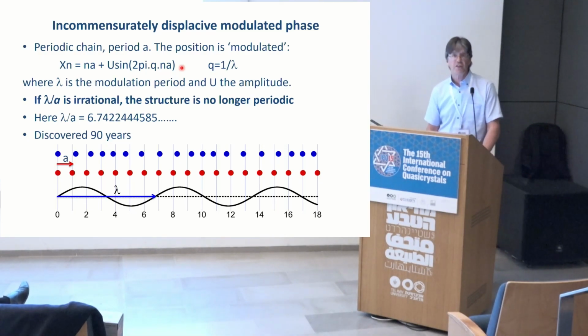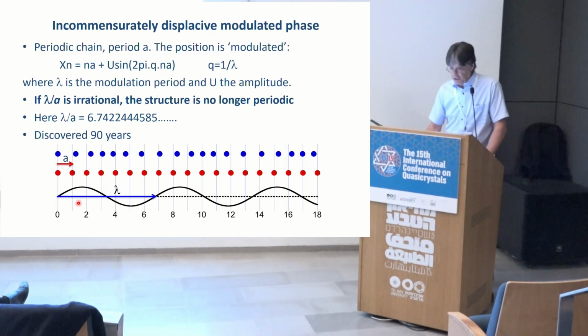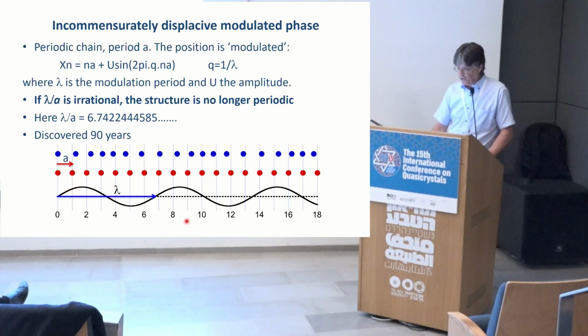And this is actually a pretty simple situation. You start with a periodic one-dimensional system. You apply on it a distortion, which is sinusoidal here, with a wavelength lambda. And if the ratio of lambda over a is irrational, the obtained structure, which is shown by these blue atoms, displaced positive if it's positive, negative if it's negative, is no longer periodic and never repeats itself because lambda over a is irrational. So already we have here an example of a non-periodic structure.